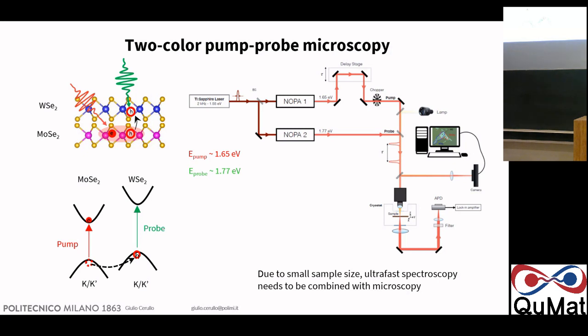Now, in order to study this material, we had to develop a two-color pump-probe microscopy. So we had to focus our ultrashort pulse to very small areas. Here I don't go into the details. We can select one color for the pump and one color for the probe, and then we can focus both to maybe 1 micron. And now, what is our goal? Our goal is to pump only the low bandgap material, the MoSe2, and to probe at the A exciton of the WSe2, of the higher bandgap material. So what do we expect to see? Since we expect this hole transfer, we expect to see the bleaching only when the hole transfer is indeed happening.